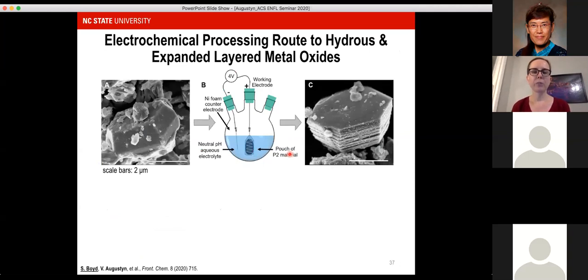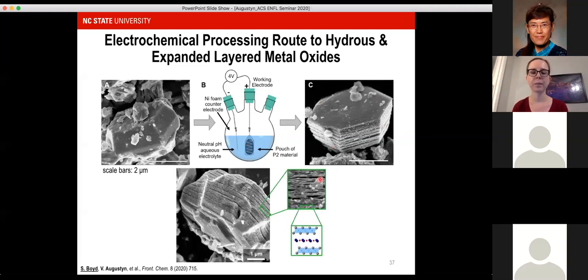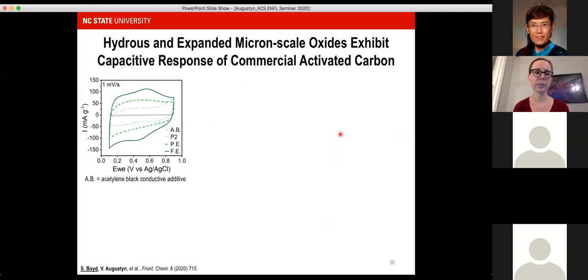So we came up with a bulk electrochemical expansion process. We took the P2 oxides and put them into a pouch cell made from dialysis tubing, so nothing fancy, and applied a very high voltage between this and a counter electrode to drive out as much sodium as we could. What we get out of that is an expanded and hydrated material, but now it's a powder that we can assemble into electrodes. If you go back to one of the earliest slides of my presentation, where I said, wouldn't it be nice to investigate the materials in between the bulk and the complete exfoliation? This is essentially that material. And what's really interesting is that now we do the cyclic voltammetry of these materials. We know from the operando X-ray diffraction results that this is due to sodium insertion and deinsertion into a hydrated interlayer, and it looks almost like a perfect capacitor.